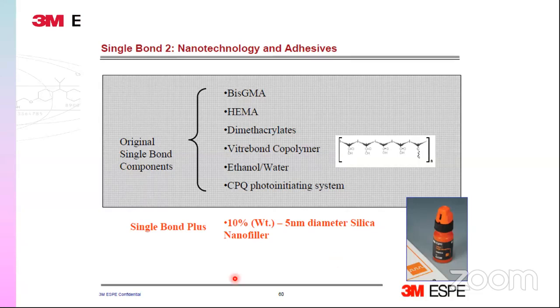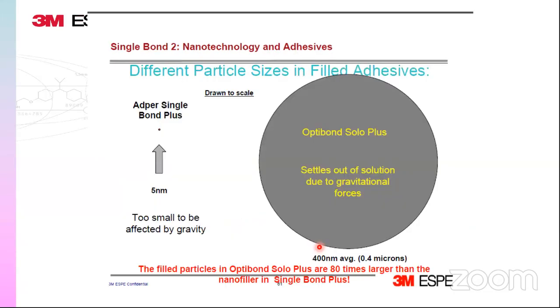Now, this bond has 10% filler loading. I told you, and the particle size is 5 nanometers. Please understand it's 5 nanometers as opposed to some other particles which could be in micron size. Now, what this does is, when I'm talking about the maximum amount of particles percolating inside my dental tubules or my collagen fibers, I'm interested in having the smallest size particles possible.